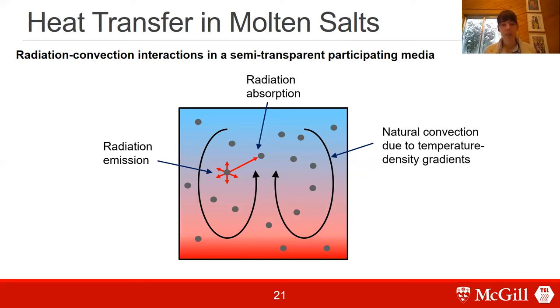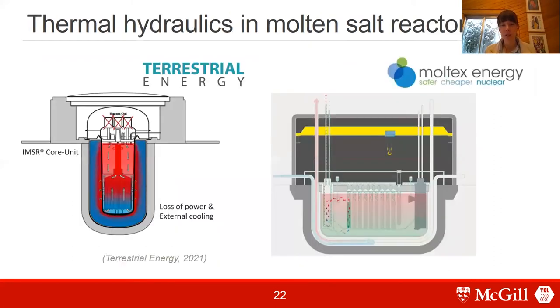And it actually has some significant implications in terms of the design of nuclear reactors. So if we look at our nuclear reactor design, the design by Terrestrial Energy, our molten salt reactor, we have molten salt flowing through the nuclear reactor core, and it has uranium fuel that's dissolved. So if we have a loss of power accident where the pumps are no longer working, what we want is to be able to have the salt continue to flow via natural convection so that we can continue to remove the decay heat in the nuclear reactor.